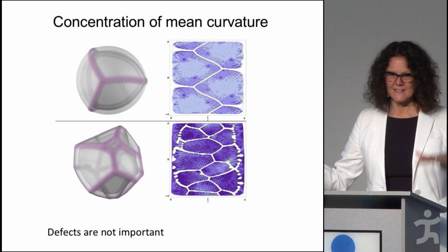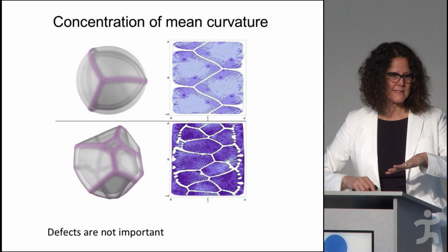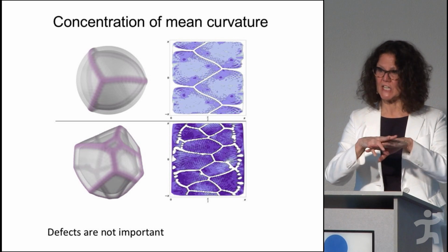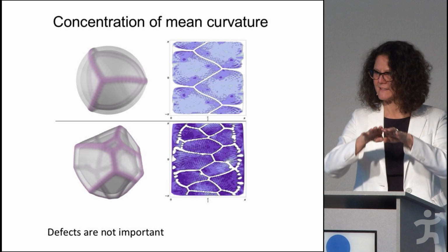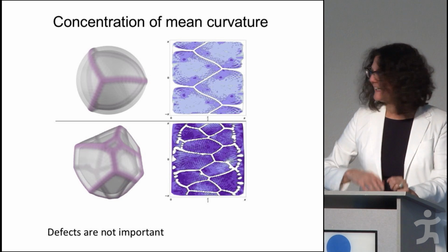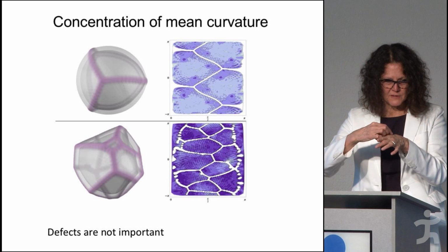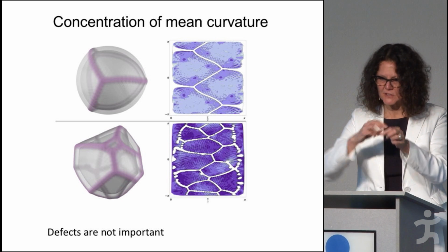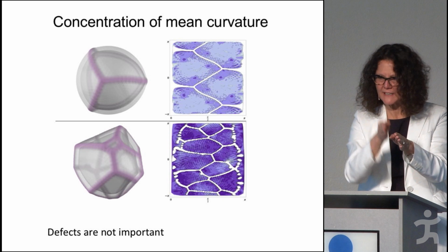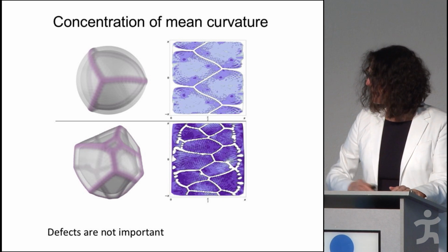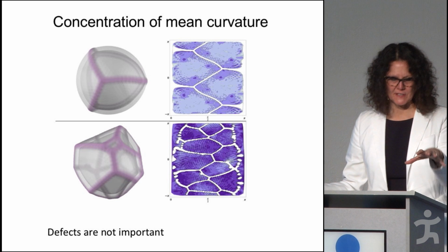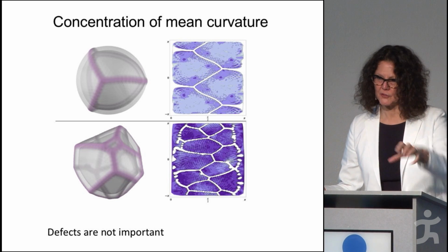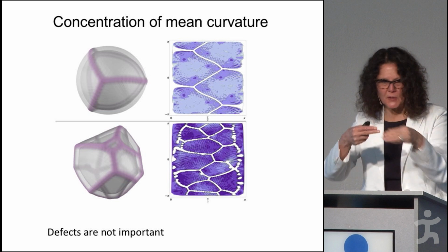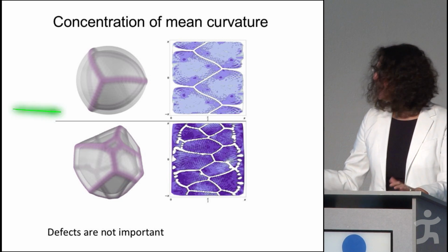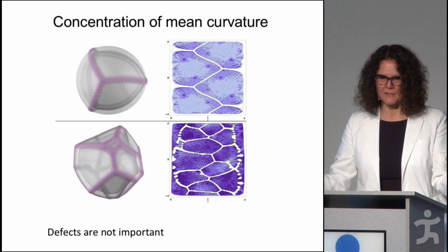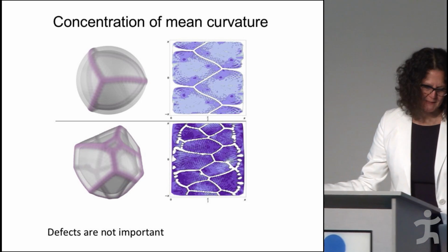As I told you, the defects are still there because my system has fixed connectivity. We didn't really change the mesh. We just minimized and let it change shape. And the way it buckled was by something that we call concentrating the curvature. Concentrating along these lines, so it bent more, the mean curvature was very high there. So that's what other physicists study, for example, how you crumple a piece of paper. If you take a piece of paper and do that, it has the same principle. You concentrate the curvature. So it's very nice when things can be explained from different fields in this phenomenon.